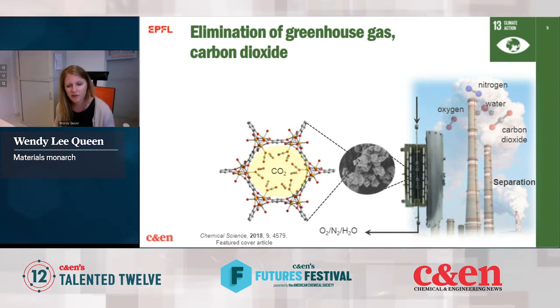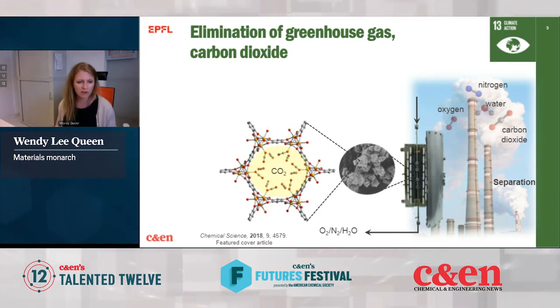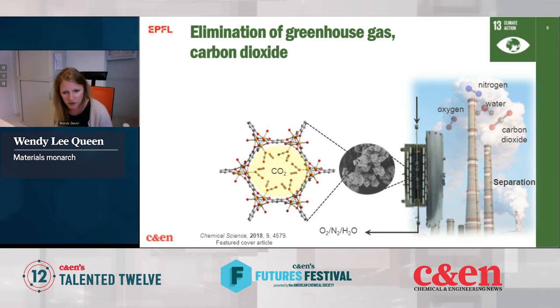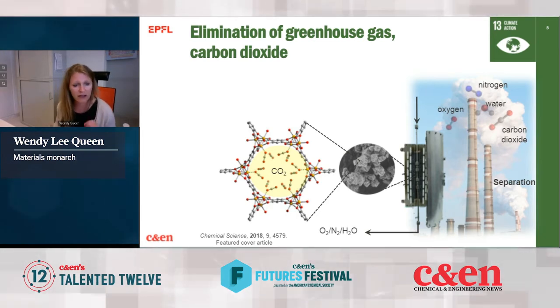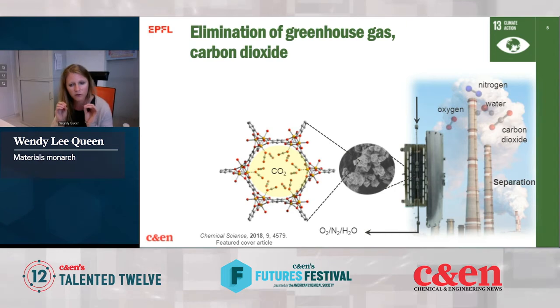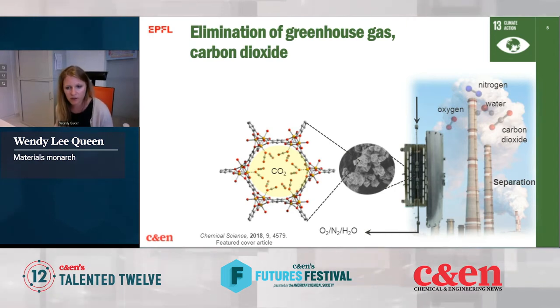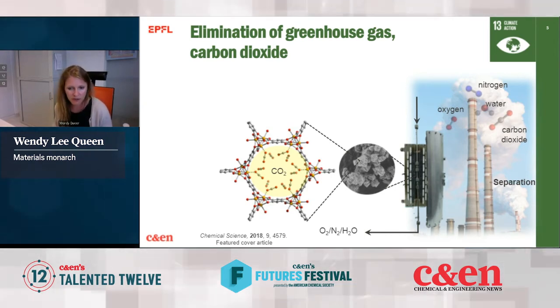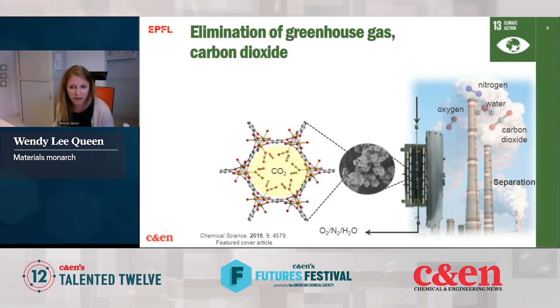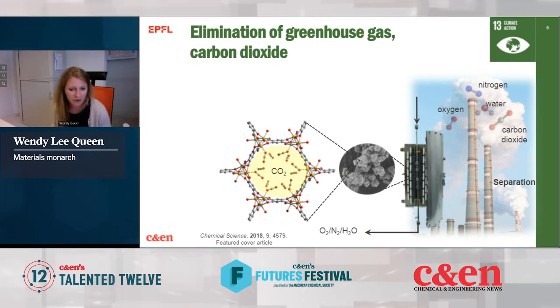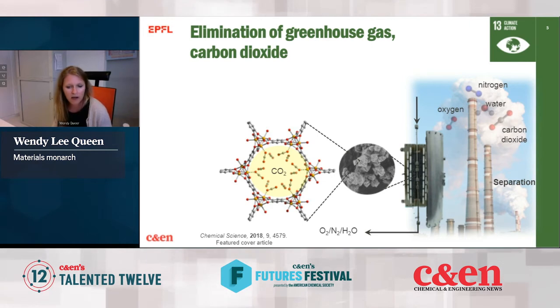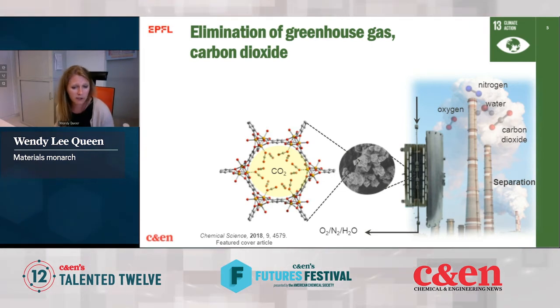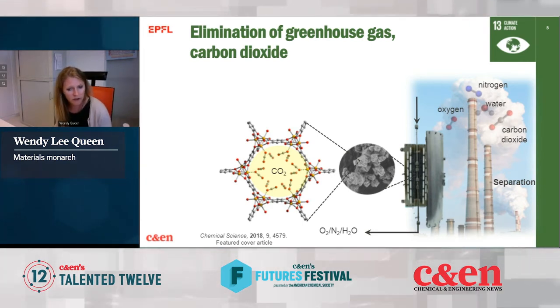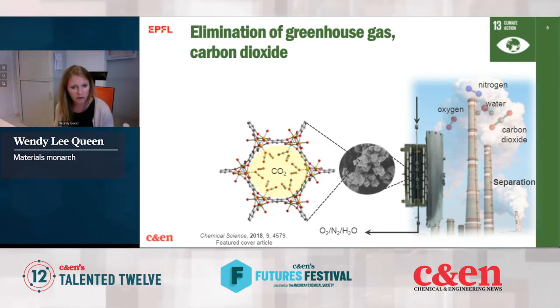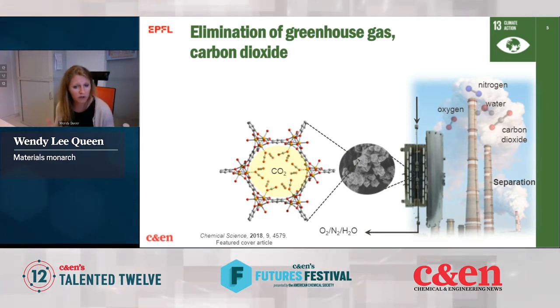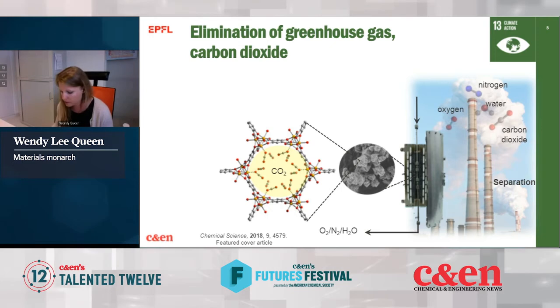And the key is that these small molecules have very similar sizes and shapes. And so if we want to capture CO2, we really have to design a material that has molecule-specific interactions on its internal surface. So then what we can do is simply stream the gases through our materials. We can capture that CO2, as you can see here, and then we can emit the less harmful gases, for instance, into the atmosphere. Once our materials are saturated, you can, for instance, heat those up and release that CO2 if you wanted to store it, for instance, long-term underground.